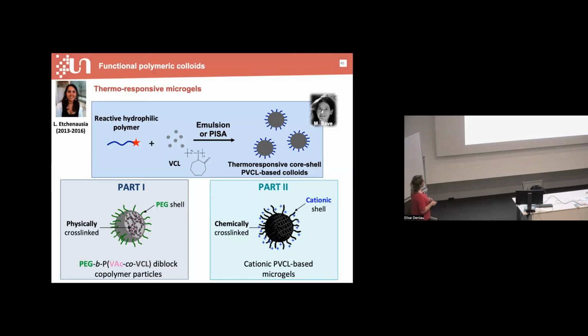So the second part of the presentation I want to show you today is the elaboration of colloid dispersions, either for environmental application and later for energy application. This work is done together with my colleague Inpo Motsav, and we first synthesized well-defined thermoresponsive microgels with the PhD of Laura Echenozia, consisting of vinyl caprolactam thermoresponsive units. And we elaborated two kinds of system, one physically cross-linked microgel using a hydrophobic vinyl acetate unit, and one chemically cross-linked using a classical cross-linker.